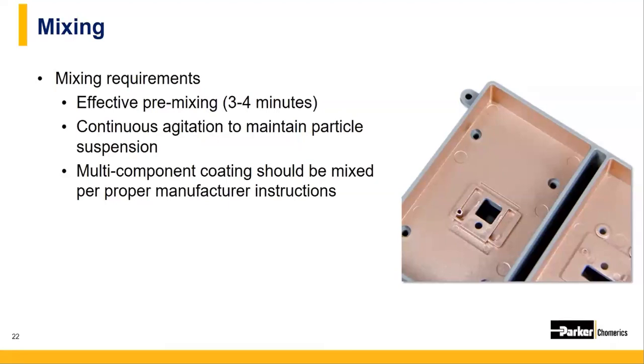It can also be mixed by hand with a large spatula, but should be a completely homogeneous suspension before you start the spraying process. At the same time, the paint should be constantly mixed and agitated throughout the spraying process, probably every 30 to 60 seconds at least. The real key is to make sure that no unmixed material remains on the bottom or sides of the container.